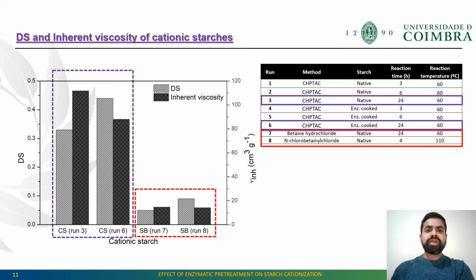The product from the esterification reaction showed a lower range of viscosity. Hence, the same reaction was not performed using cooked starch, as starch granules already face so much hydrolysis during the esterification reaction. Also, a lower DS of around 0.1 was obtained in runs 7 and 8. Besides, a brown color product was also obtained in run 8, which could be due to the more severe degradation of starch granules at high temperature.